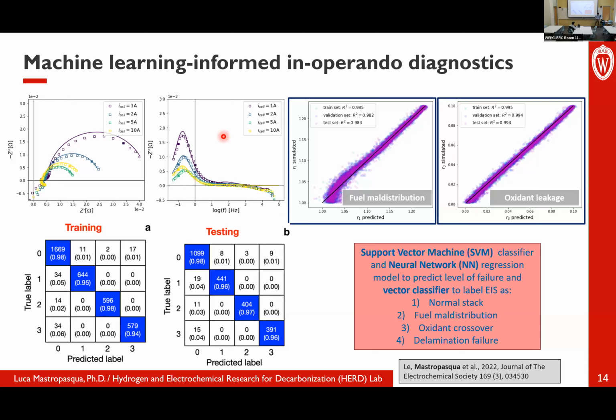So we took these electrochemical impedance spectroscopy data and we created a machine learning model that was able to tell us whether that spectrum was from a healthy cell or a defective or faulty cell, and which fault was associated with which spectrum. On the right-hand side, you see examples of the results of the machine learning algorithm testing many of these spectra. If the predicted value was 1.1 for this method, fuel maldistribution, and 0.05 for this other degradation method, oxidant leakage, that was the healthy condition. Beyond those, all the other values were for faulty cells.